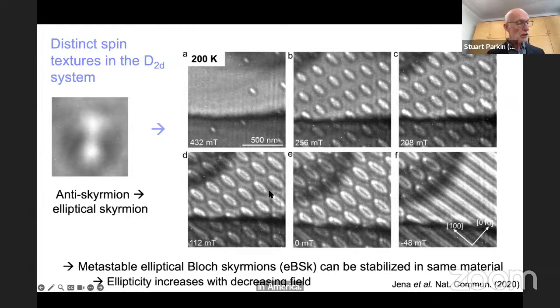So it turns out these dipole fields play another important role in that they can allow for a different type of structure in the same Heusler compound, the same manganese 1.4 platinum tin compound. Jagannath Jena, a student, now a postdoc in America, found that surprisingly, he could see another non-collinear spin texture that had not been predicted, and was a surprise because I haven't really discussed, but the skyrmionic objects are of interest because they're topological.